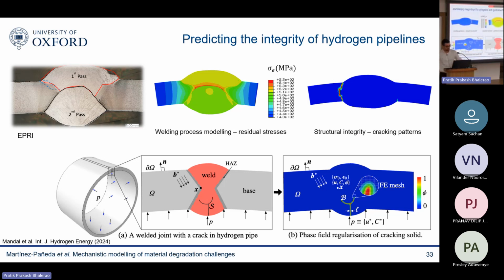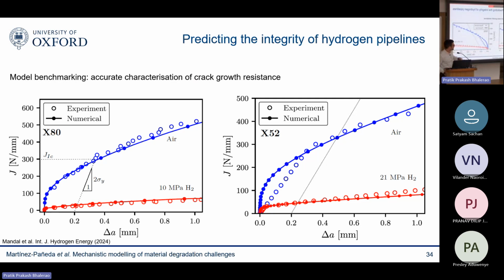But the idea is simple. You first do the welding model, and then you predict the fracture. So you get residual stresses, you get phase fractions, you get the microstructural heterogeneity. But before I do so, of course, the first thing we did was to simulate R-curves, so crack growth resistance, in those pipeline steels, with and without hydrogen. And as you can see, the model seems to be in very good agreement with the experiments. So that gave us confidence that the model is able to capture bulk behavior, is able to capture how pipeline steels behave in the presence of hydrogen gas.